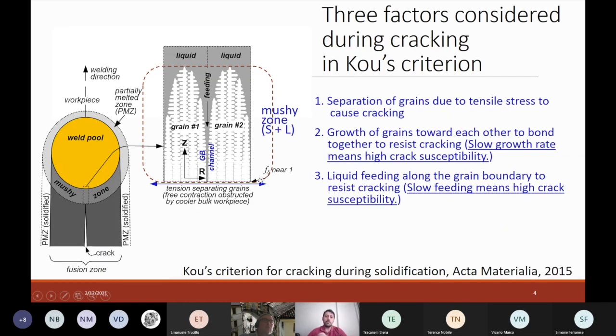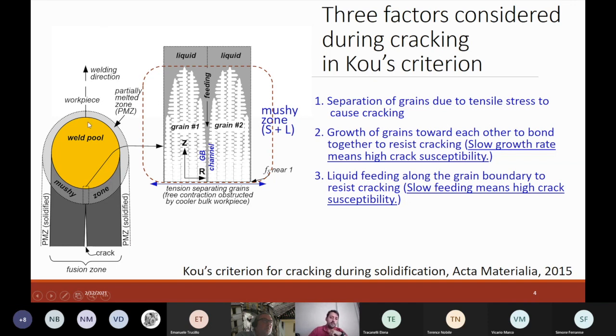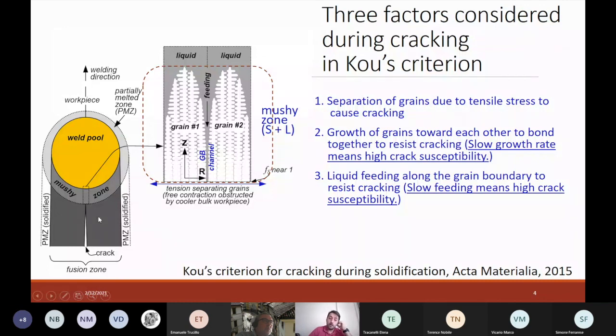Now let me show you what's going on in welding with this welding sketch. We have the weld pool, and the welding torch is normal to the page, moving in this direction. When the weld pool proceeds in this direction, it leaves behind a mushy zone. The mushy zone is the place where solidification happens — we see both solid and liquid there. After that, we have completely solidified weld metal. Cracking also occurs in the mushy zone of the weld.